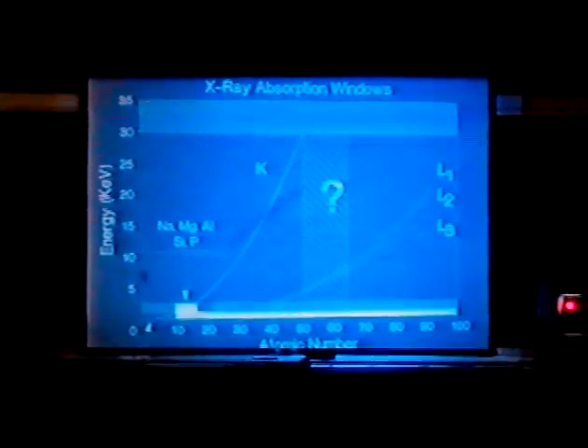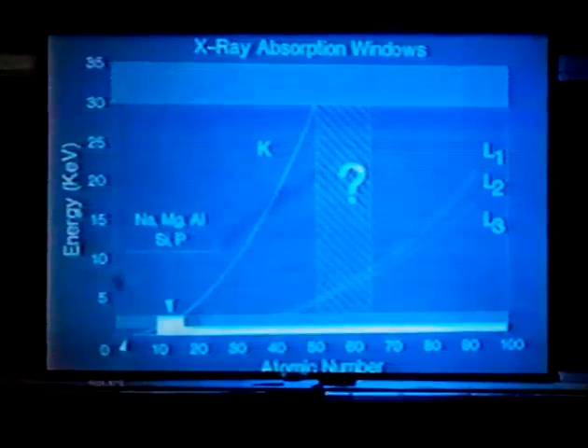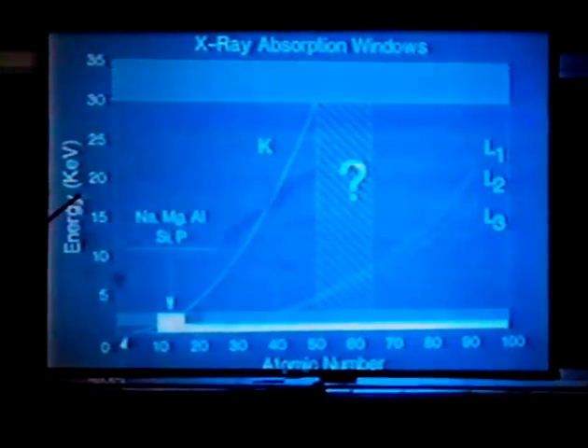This plot shows the applicability of these kinds of X-ray absorption experiments. This is a slide I got from someone else. What's plotted here is energy of the photons versus atomic number. And first of all, these hatch marks represent areas that are inaccessible in energy. Up here, above 30 keV, that's about a third of an angstrom, the energy of the photons is just getting too high, and they're either hard to work with or unavailable.